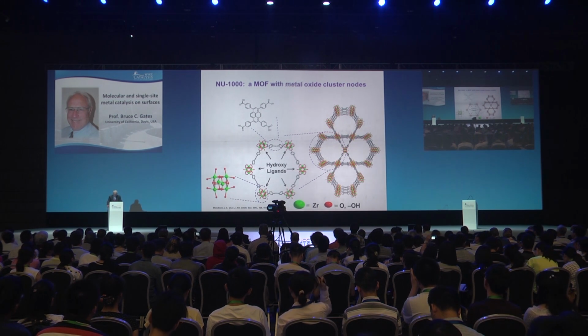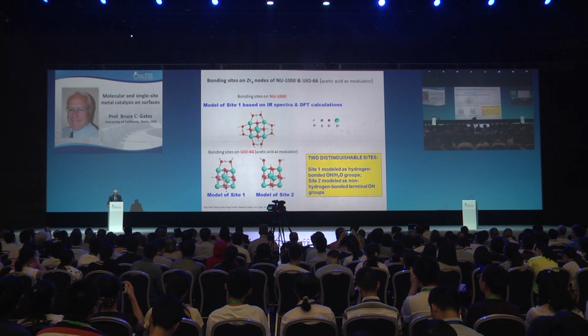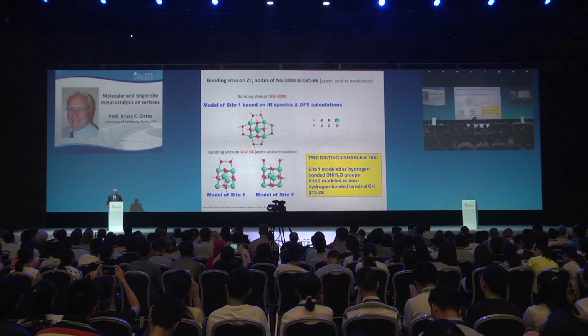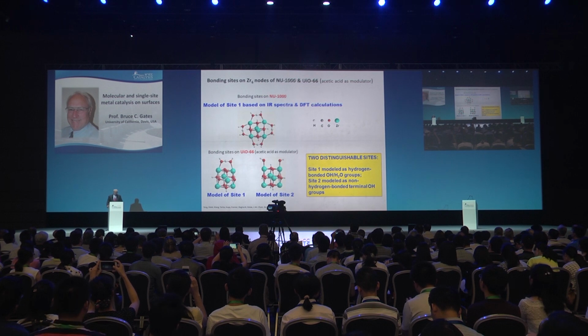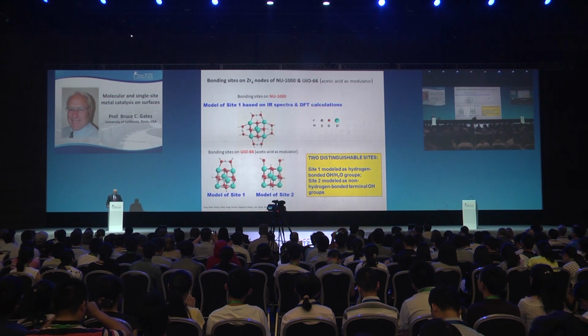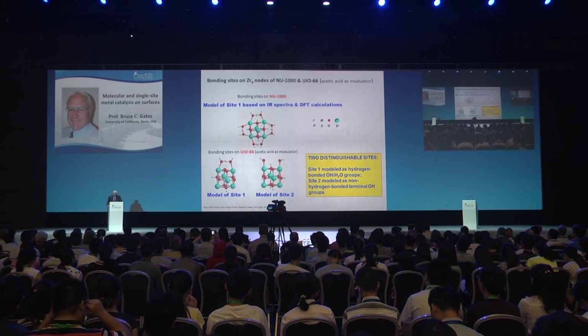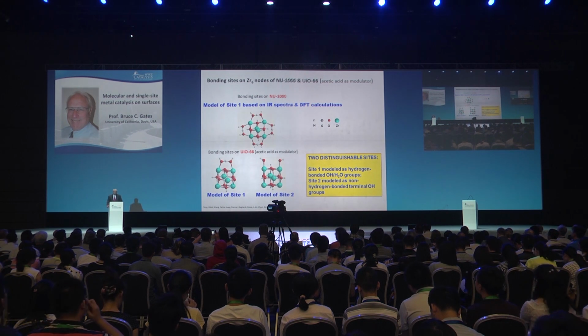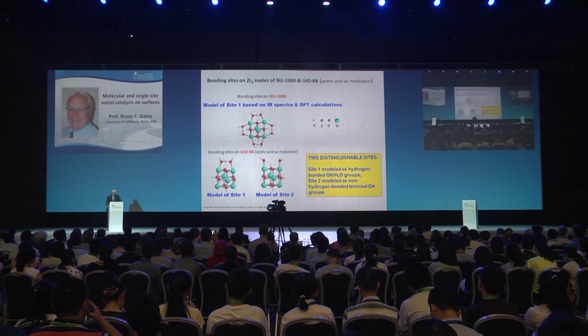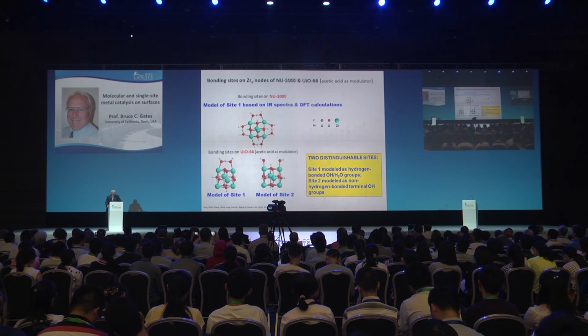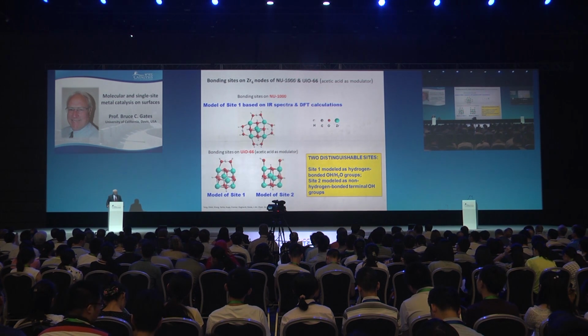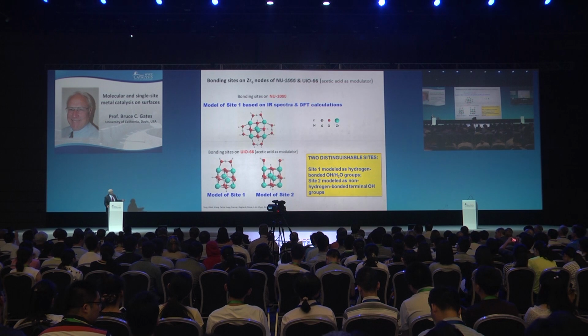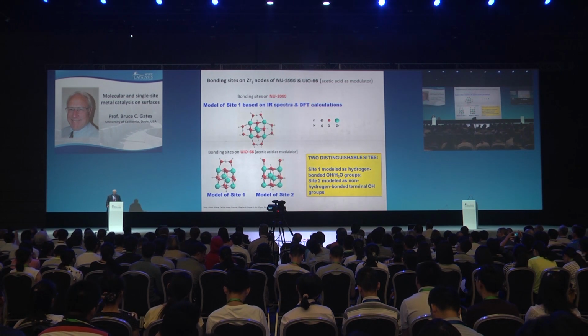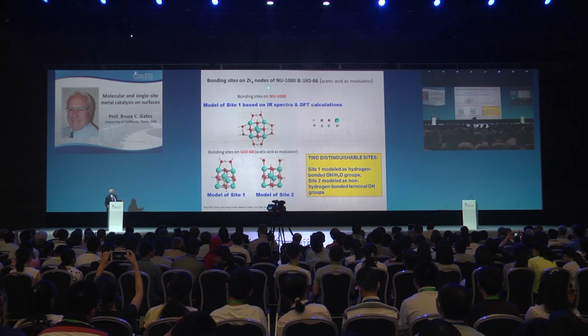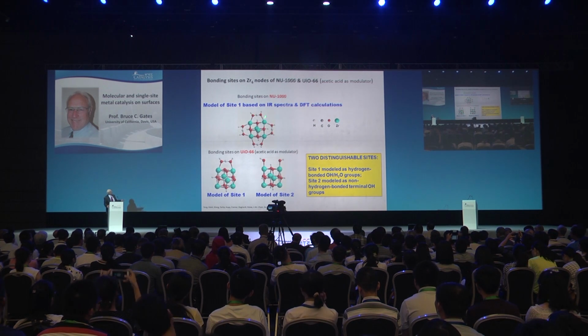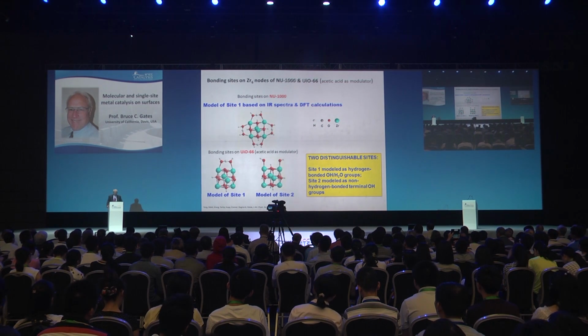What do we know about those nodes? Well, people have done calculations and infrared spectroscopy to form models of the structures of the nodes. They're like metal oxides, so they have hydroxyl groups and aquo groups, giving sites for bonding of metal complexes. Here's a model of one node—DFT supports this one strongly, it's quite stable. You see an OH group and an aquo group, and they're close, so they're hydrogen bonded to each other.